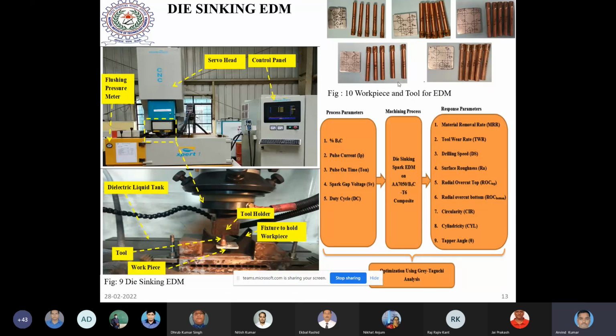And this die sinking method I have used. So these were the parameters which I have selected. This is the composite, and here is the copper pin I have used as a tool. And of course, the hardness of our composite was very high compared to this copper. And since I have used electro discharge machining, the setup is like this.